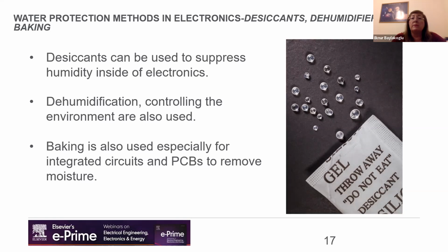And in addition to this, the storage environment of the electronic spares for the long-term project is a critical issue. Because all plastic integrated circuit packages have a tendency to absorb moisture. During the surface mount assembly, this moisture can vaporize. Actually, we mentioned this, and this can cause cracks. We mentioned the popcorn effect, and since these plastic packages absorb moisture, care must be taken to prevent them from exposure to greater than 10% relative humidity actually.